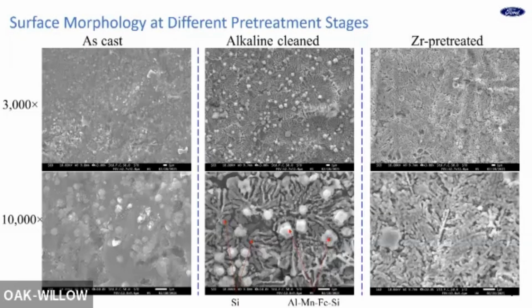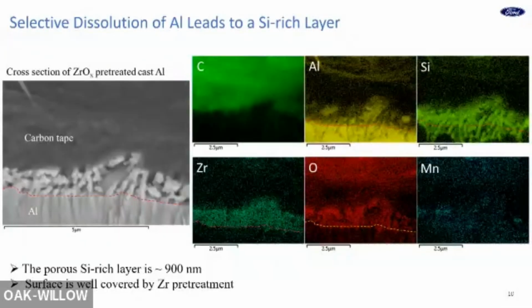So it seems there's a lot of etching on the surface, and also we put some zirconium on the surface. We did further work to understand how thick this porous layer was and how the zirconium forms on the surface. So this is the cross-section of a pre-treated sample. We put a carbon layer on the surface just to protect it, to avoid etching during the preparation process. The red line here is the interface between the porous structure and the metal substrate.